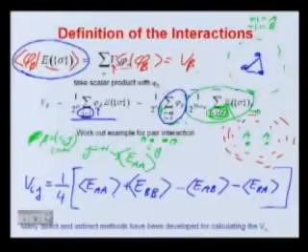Typically what you'll find is that these V's are much, much smaller than direct interaction energies, and the reason is they contain an enormous amount of cancellation. If you think about it, this is the AA energy, the BB energy, and -2 times the AB energy. So they're often several orders of magnitude smaller than direct interactions, if such a thing were to exist.